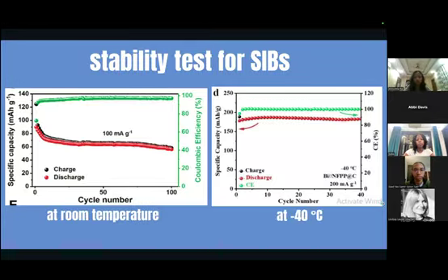So this slide talks about the cycling stability of the sodium-ion battery. The x-axis shows the cycle number, which is how many charge and discharge cycles the battery went through. The left y-axis talks about the specific capacity, which is the amount of charge stored per gram of active material. And the right y-axis shows the Coulombic efficiency, which measures how much charge put in during charging can be recovered during the discharge process. So if the Coulombic efficiency is 100%, that means that all charge is usable.